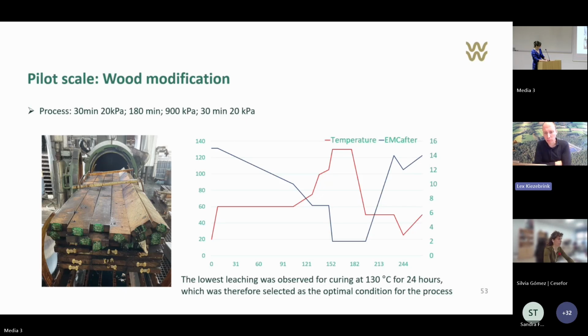the moisture evaporates slowly out of the wood. We have to be at really dry levels before we can raise the temperature to about 100 degrees, and then we have a steam drying process to about 110 degrees. And then we elevate the temperature to 130 degrees for 24 hours, because we noticed that we needed this curing temperature to prevent leaching. After this process, we also did some remoistening to make sure that the wood relaxes a bit. So that's about it for the curing process.